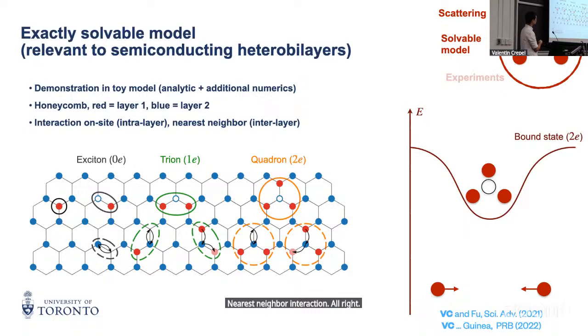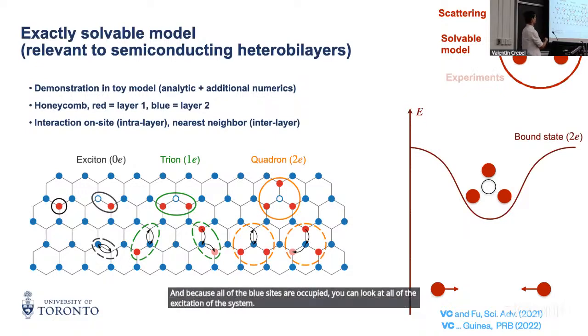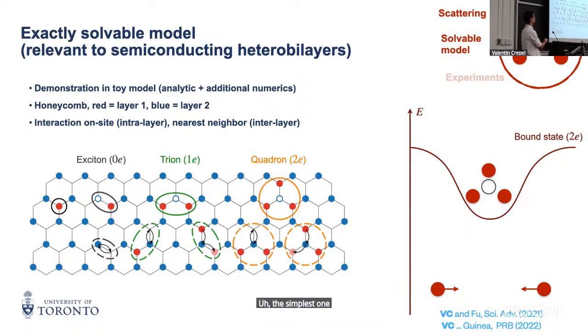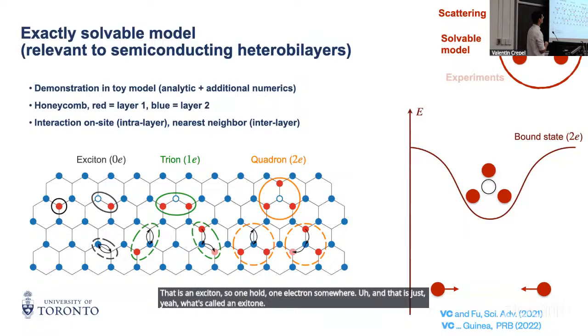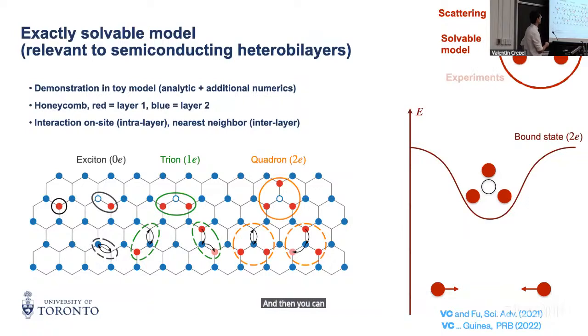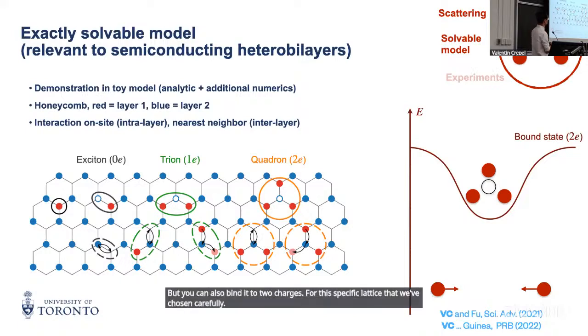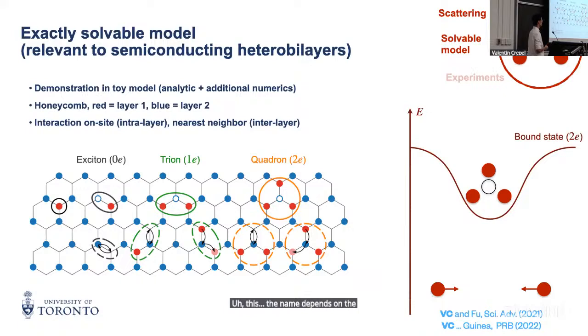And because all of the blue sites are occupied, you can look at all of the excitations of the system. The simplest one is moving one blue dot to the red lattice. That is an exciton, so one hole, one electron somewhere. And then you can bind that exciton to one additional charge. This is called a trion. But you can also bind it to two charges for this specific lattice that we've chosen carefully. The name depends on the literature, but let's call it a quadron.